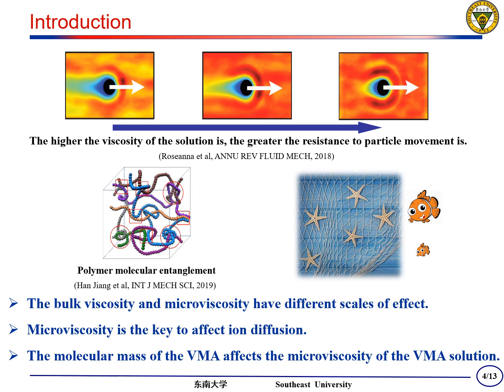Because the pores of entanglement between adjacent polymer chains of VMA will become large, providing free paths for ions to go through, just like they go through water. Although the solution has a remarkably high viscosity in such cases, therefore, determining the suitable molecular mass range is essential for mitigating chloride diffusion.